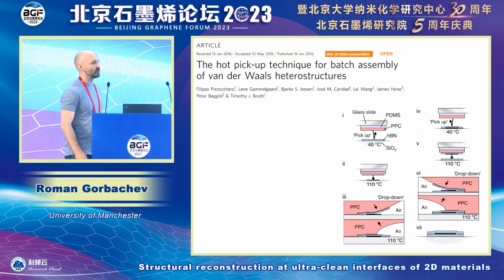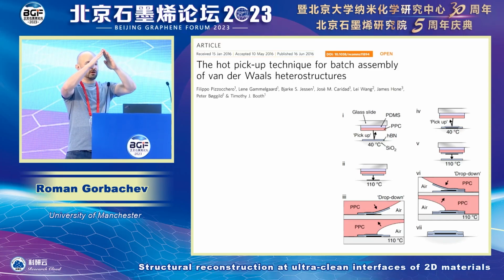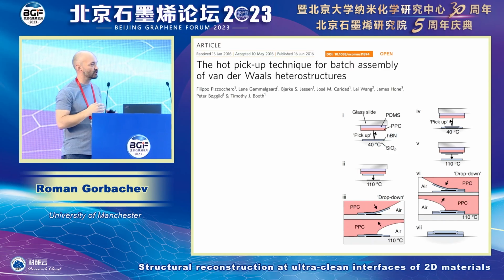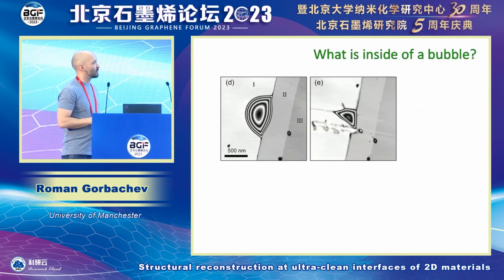The key really to making cleaner structures is higher temperature and slower interface collapse. So when you put these materials together, you're basically trying to collapse them as slowly as possible. And as you collapse them, you squeeze out all the contamination that has been building on the surface. And because everything is done in the air or in argon, there is a lot of hydrocarbon contamination and gases on the surface that is being trapped. And we're kind of trying to just squeeze them out when we do that. So with this technique,